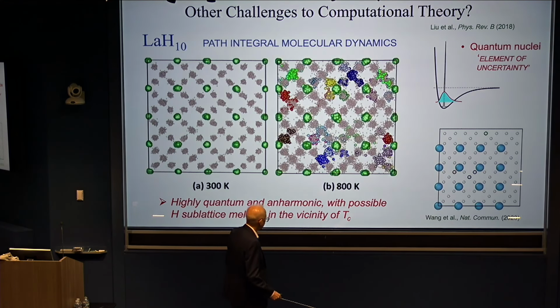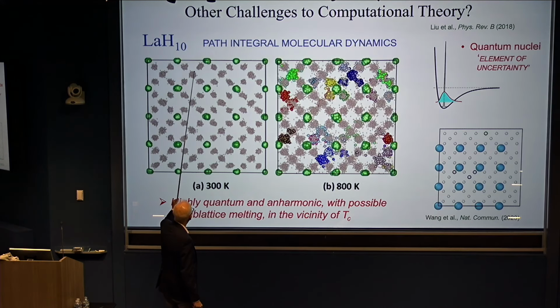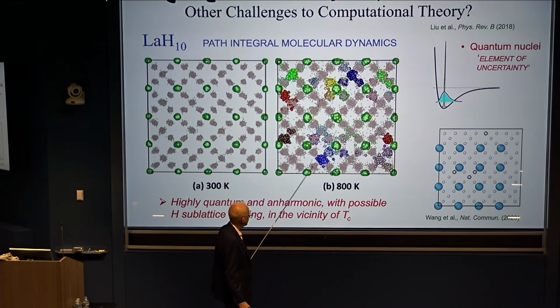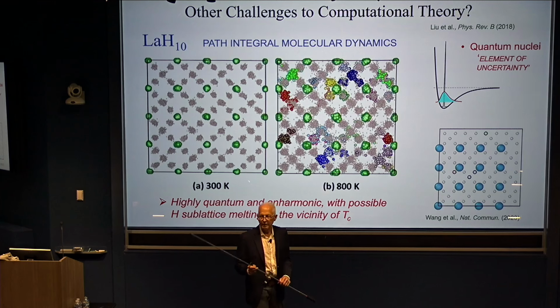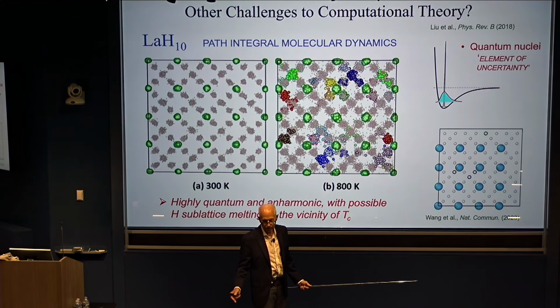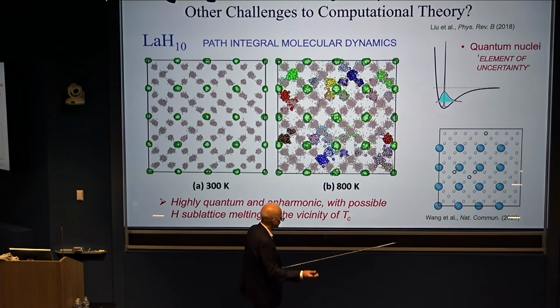And this is something we noticed when we did our first calculations on lanthanum H10. We did what's known as path integral molecular dynamics, where we tried to take into account this quantum character. These beads here are the trajectories of the particles during a simulation. And what you find is even at room temperature, and this is in the vicinity of TC, there's a lot of quantum character. And if you increase the temperature, you in fact see what looks like sublattice melting. So you have this curious situation where in the vicinity of superconductivity, you also may have a fluid state or a near fluid state of the hydrogen. This is not what goes into the theory of superconductivity. So there's a real problem.